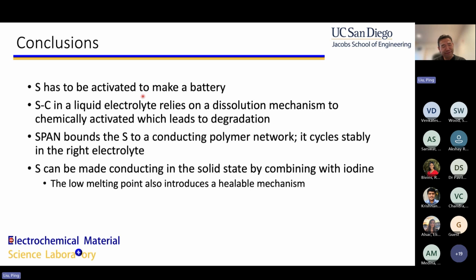Elemental sulfur itself can never make a battery. In order to make a battery, people have tried lots of different things. If you make a nanostructured sulfur carbon composite, you put in a liquid electrolyte, it does cycle, it does discharge and charge, not for long. And it relies on a dissolution mechanism. Basically, you picture sulfur as like rock, but the electrolyte is kind of like a corrosive agent. You gradually dissolve it away and then reprecipitate it. In that case, you don't need to rely on the electronic conductivity of sulfur to have a chemical or electrochemical reaction.